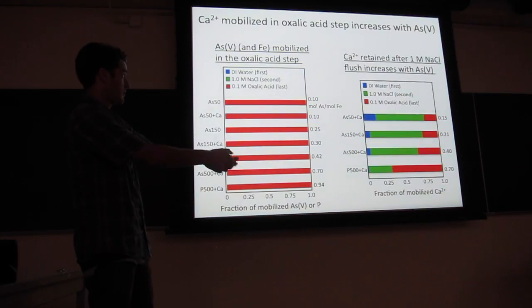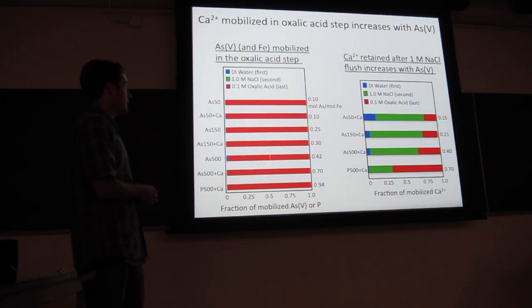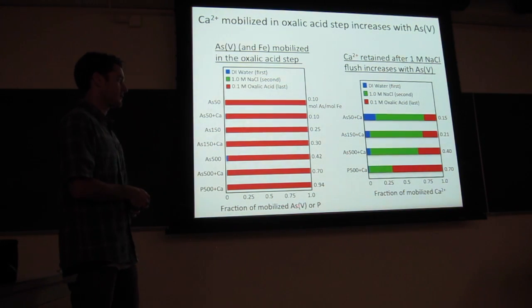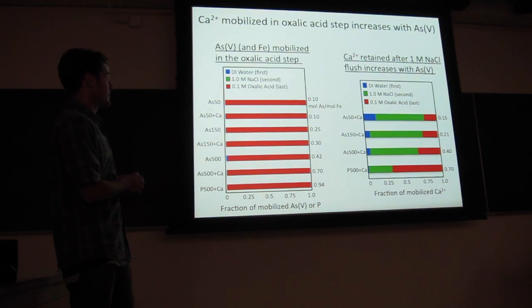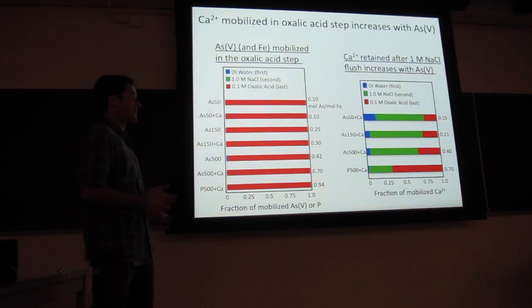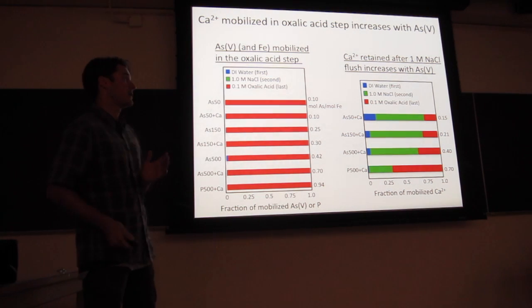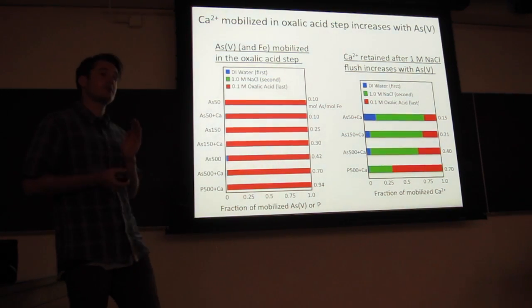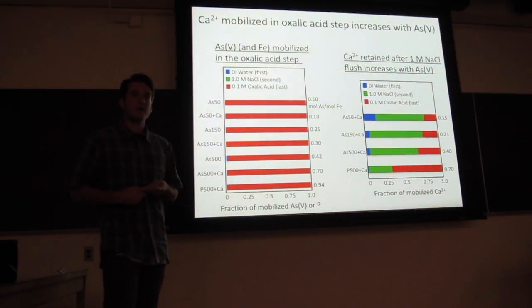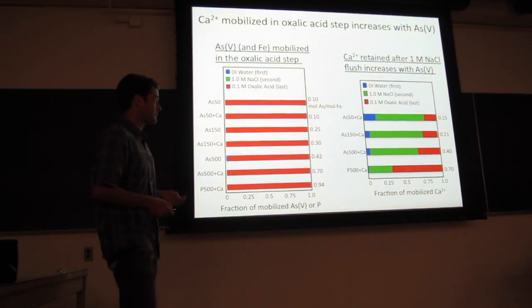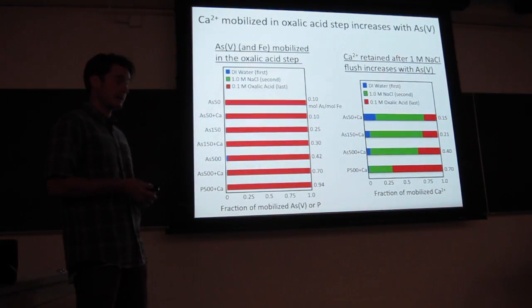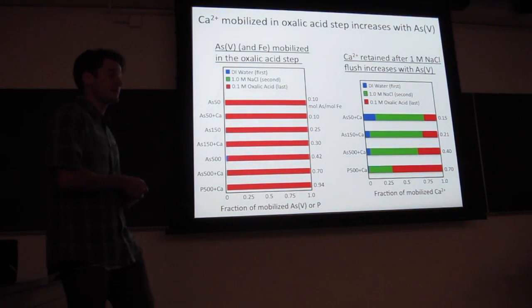All right. So on the left, I'm plotting here the fraction of mobilized arsenic or phosphate, and you can see the three different steps up here, but it's very clear arsenic and phosphate are only mobilized in the oxalic acid step. And if I were to plot the fraction of mobilized iron, you would see the exact same trend. And so that's telling us that there's a very strong coupling between arsenic and iron, or phosphorus and iron, in our system, and that the mobilization of arsenic is primarily contingent on the dissolution of the solid phase, at least in these experiments.